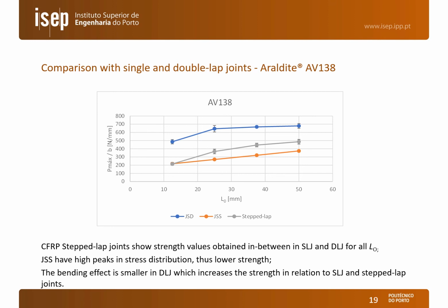On the other hand, the results for double lap joints presented in blue are much higher than both for the single lap and step lap joints, and this is because we have the smallest peak stresses, because we have an almost elimination of the bending moment in the joint, but also and mostly because we have the application of double the shear area of the adhesive for the same overlap length. So it is normal that the results are much better with this joint configuration than with the other two configurations.